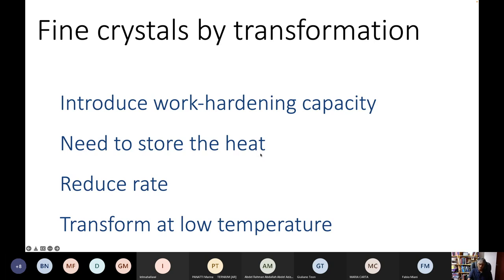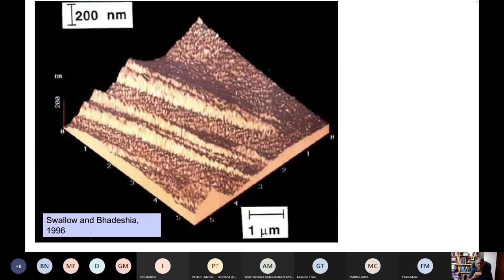How do we store heat? The transformations which release the least heat of transformation are those which store the heat in the form of elastic strains. If you are making very thick samples, then probably martensite is not the right structure to think about. But in the case of bainite, the displacements associated with the transformation store quite a lot of energy inside the material in the strain fields of the shape deformation. So using a displacive transformation will give us heat of transformation stored inside the material, and therefore less is released and the recalescence problem is reduced.